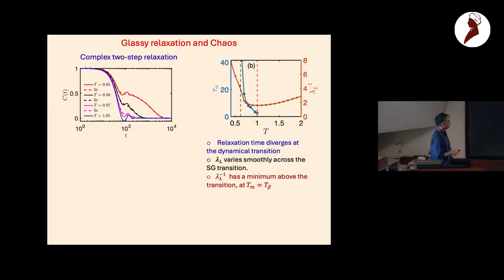And you can try to obtain from here the alpha relaxation time, and the alpha relaxation time of course diverges as you approach this dynamical transition. I have plotted on the same plot lambda L inverse, which I have shown earlier, which had a peak above the dynamical transition. So lambda L inverse has a minima above the dynamical transition. So one answer is that lambda L inverse doesn't diverge at the transition, so it's not related to this diverging time scale. This is not very surprising actually, but I'll not go into that.